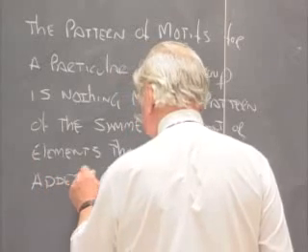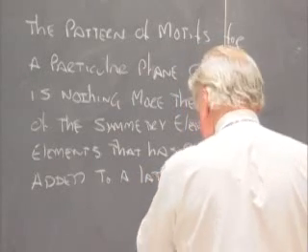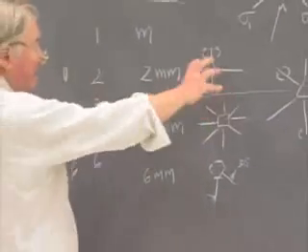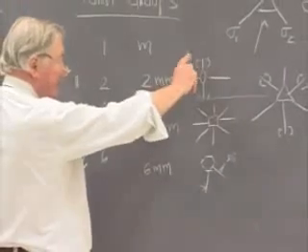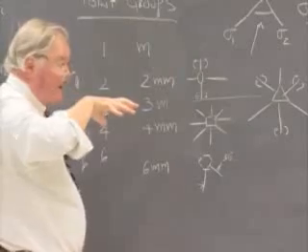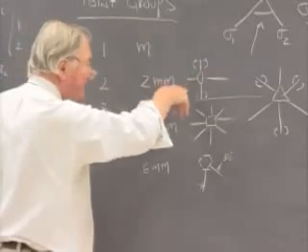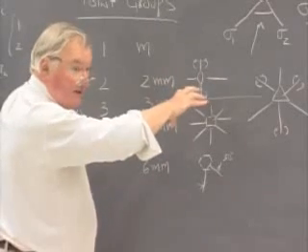That we've added to a lattice point. So in other words, if we take 2mm and drop that into a rectangular lattice, the pattern is simply going to be these 4 atoms related by 2mm hung at every corner of the lattice. If you add it to a centered lattice, these would be hung at every corner of the lattice and also at the centered lattice point.